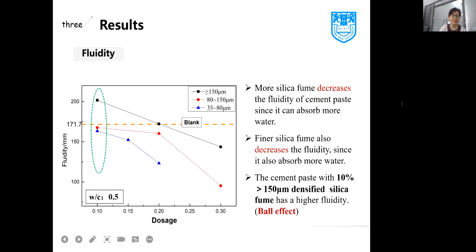We also studied the fluidity. More silica fume decreases the fluidity of cement paste since it can absorb more water. Finer silica fume also decreases the fluidity since it also absorbs more water. The cement paste with 10% densified silica fume 1 has a higher fluidity here since it has the ball effect.